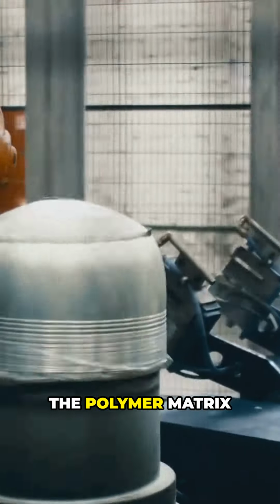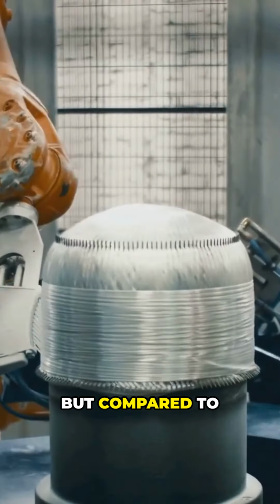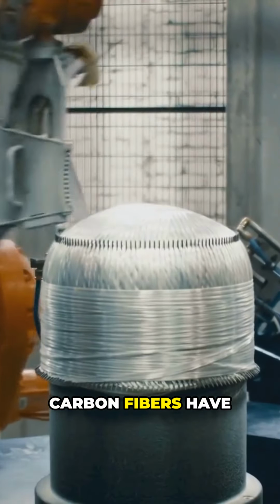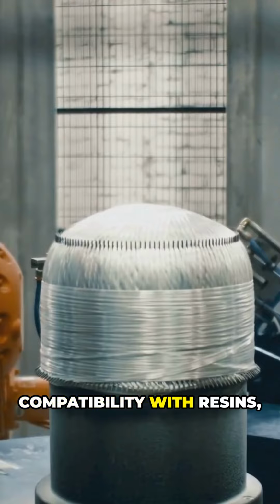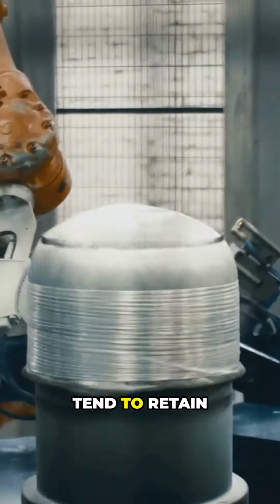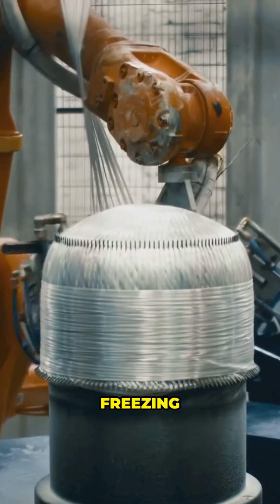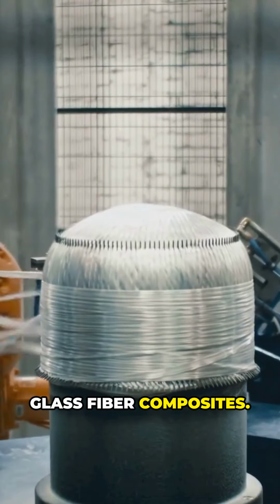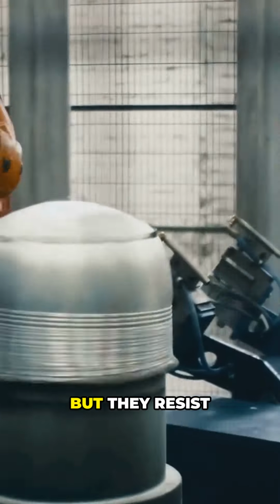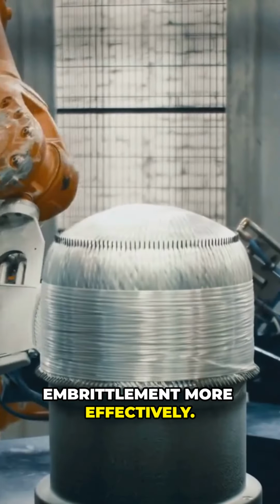Matrix. Again, the polymer matrix is the weak link, but compared to glass fiber systems, carbon fibers have better thermal compatibility with resins, so the mismatch in contraction is less severe. So overall, carbon fiber composites tend to retain strength and stiffness better at freezing temperatures than glass fiber composites. They still face reduced toughness, but they resist cracking and embrittlement more effectively.